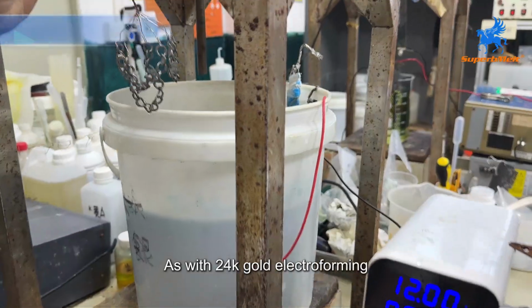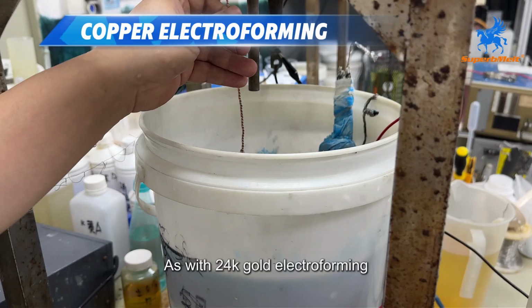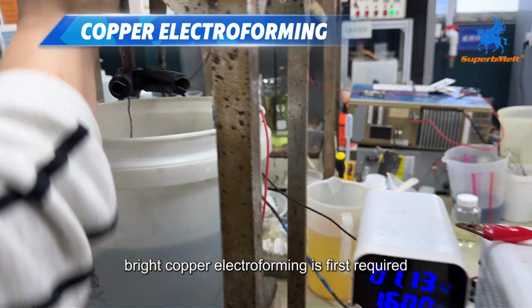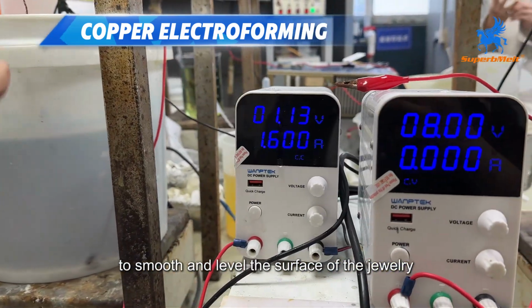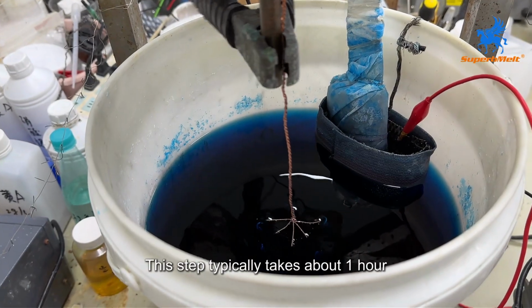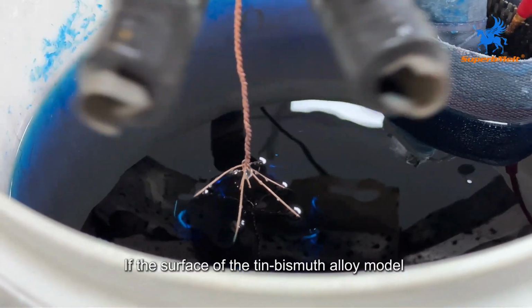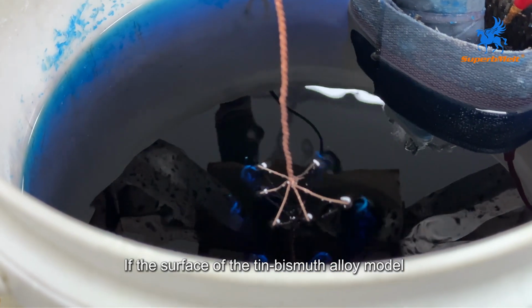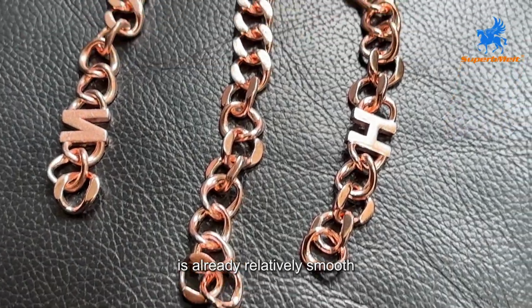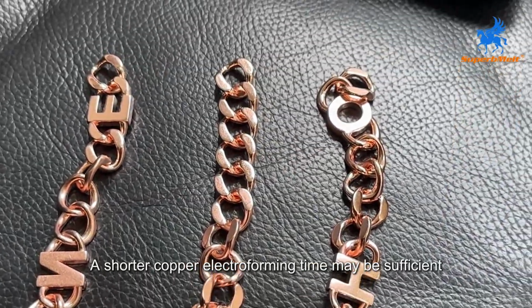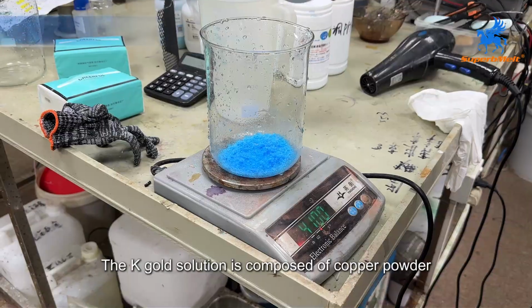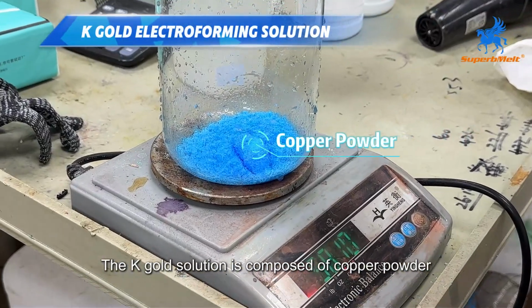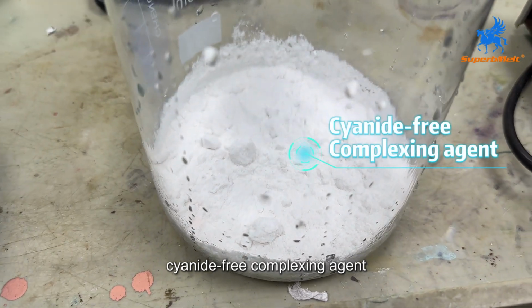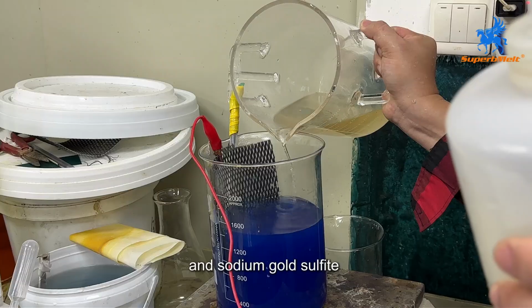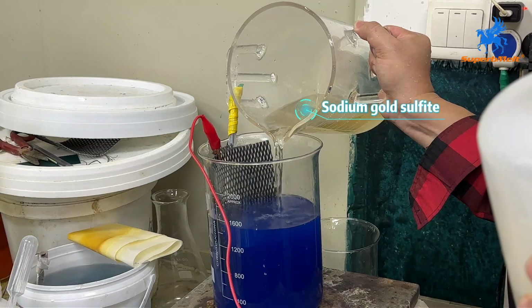contamination. As with 24K gold electroforming, bright copper electroforming is first required to smooth and level the surface of the jewelry. This step typically takes about 1 hour. However, if the surface of the tin, bismuth alloy model is already relatively smooth, a shorter copper electroforming time may be sufficient. The K-Gold solution is composed of copper powder, cyanide-free complexing agent, brightener, and sodium gold sulfite.